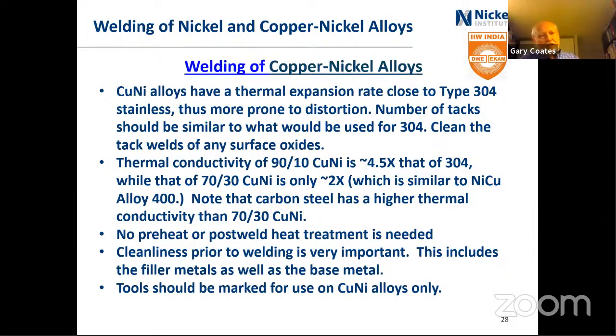And it should be noted, an interesting fact that I hadn't noted before, that carbon steel has a higher thermal conductivity than the 70/30 copper nickel. It also sucks away the heat from the weld zone. Like the nickel alloys and stainless steels, no preheat or post-weld heat treatment is needed. Cleanliness is very, very important for the copper and nickel alloys. And that includes the filler metals too.